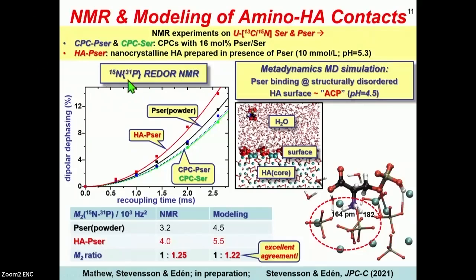So here you see some REDOR results where the nitrogen-15 NMR signal dephasing is plotted for increasing dipolar recoupling times to the surrounding phosphorus-31. Here the data in black are from the polycrystalline phosphoserine powder. The data in red are from the HA-Pser, and finally the data in green and blue are from the two cements. So from here we can see that the dephasing behavior of the two cements is almost identical. And moreover, that the amino group in the cements is slightly more distant from the inorganic phosphates as compared to the HA-Pser model system.